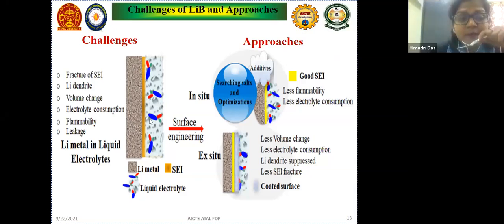From this figure, I think we can understand. So here is a solid electrolyte interface. What it does is it prevents the dendrite formation. When there is a continuous charge-discharge process, the lithium grows like a spine. So this solid electrolyte interface layer protects that dendrite from getting connected to the other side electrode, and